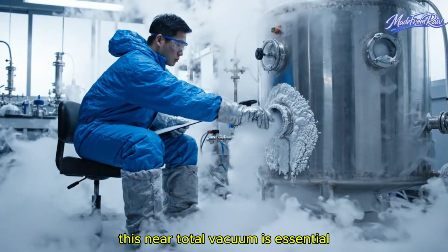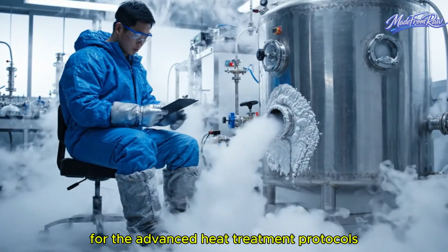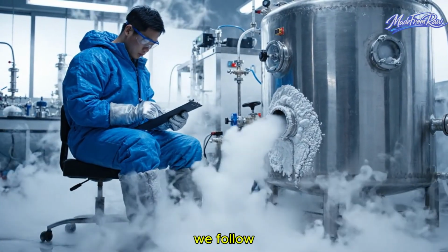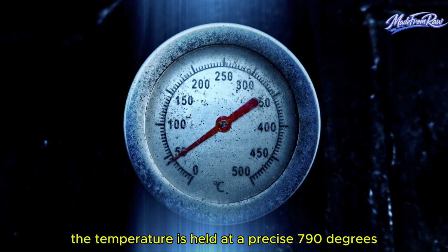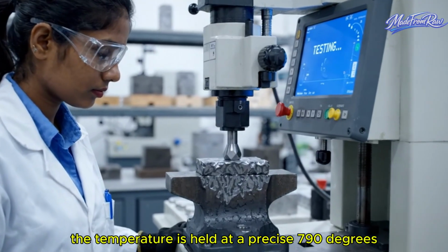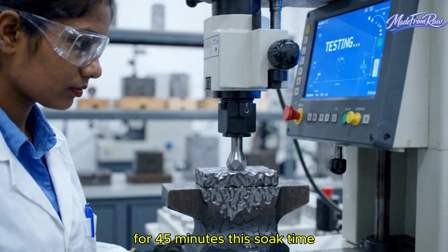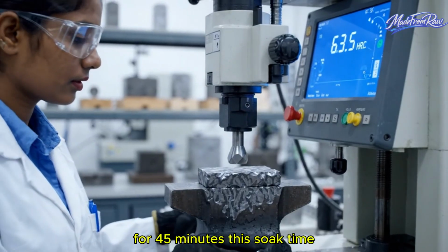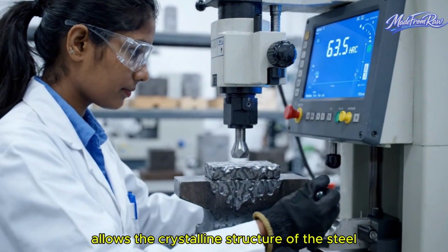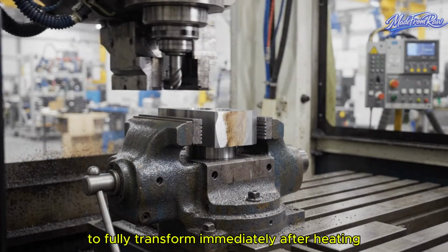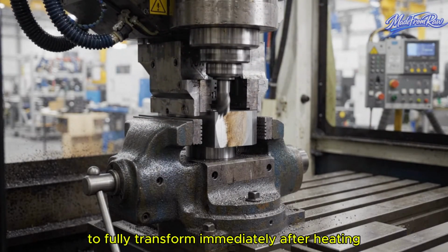This near-total vacuum is essential for the advanced heat treatment protocols we follow. The temperature is held at a precise 790 degrees for 45 minutes. This soak time allows the crystalline structure of the steel to fully transform. Immediately after heating, the steel is plunged into liquid nitrogen.